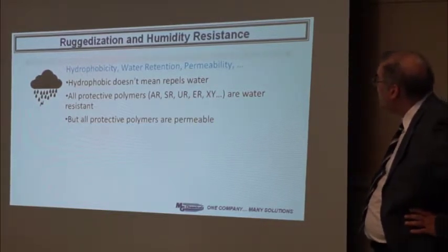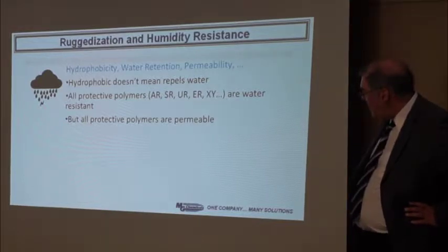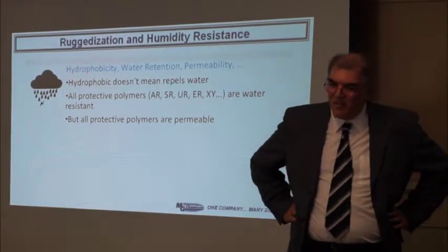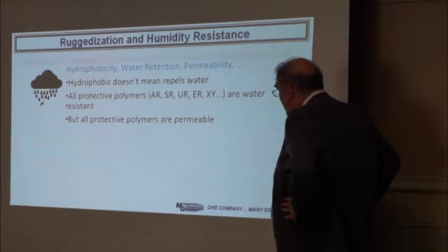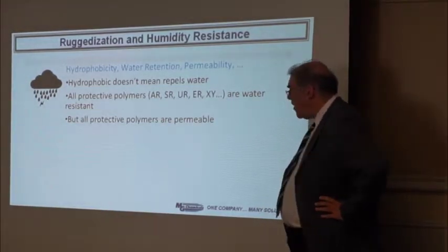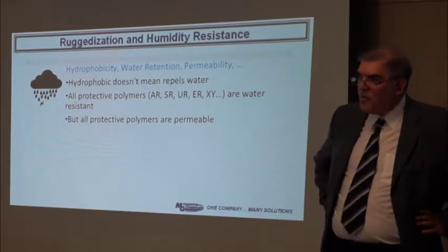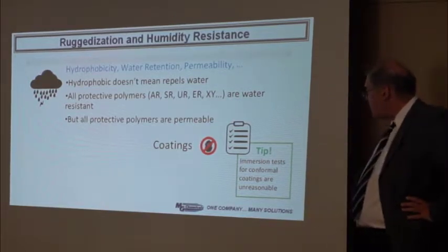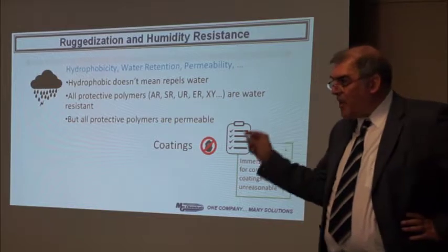Let's talk about water resistance. There are various parameters: hydrophobicity, water retention, permeability. One of my pet peeves is that people say hydrophobic means 'repels water' — that's not quite right. One thing to keep in mind: all protective polymers, no matter which one, are water resistant, not waterproof. If applied thin, they'll be water resistant. That means they're all permeable to a certain degree. If you have a thin coating and do an immersion test, it will fail — it will work for a short period of time, but it will fail. Guaranteed.